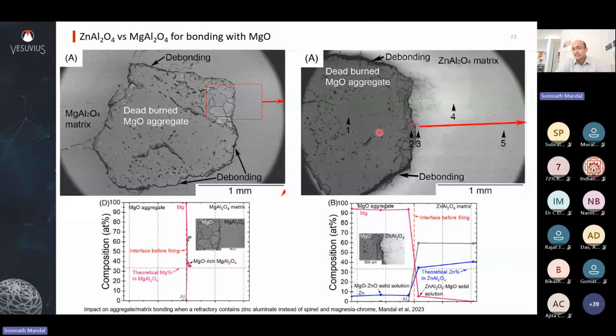In zinc aluminate, you have debonding, but you have interdiffusion or deep diffusion of zinc from the zinc aluminate side into the magnesia side. So this gives you a better advantage of being able to form a better bonding in your brick. But how do you counteract this debonding? Because your TEC is not changing due to chemical diffusion. You do that in the matrix. Let's say you look at only the matrix. 36% of your composition is your matrix. I'm just giving you an example.